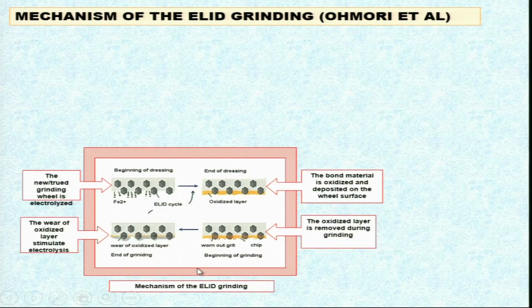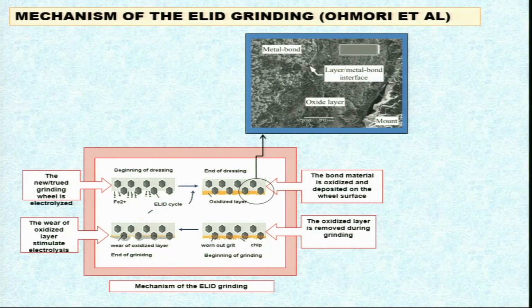You can see over here, more or less the same thing, the mechanism of the ELID grinding that we have seen. The new trued grinding wheel is electrolyzed. This is the new grinding wheel, and you can see the protrusion of the abrasive particles is quite large. But in the second phase, this is the oxidized layer being formed. So, the protrusion of the abrasive particle is continuously reducing, and if you go here, the oxidized layer is removed during grinding, because it becomes weak and larger forces are acting on the abrasive particle. So, they separate out or fracture and remove the oxide layer, and you have the worn out grit also, and chips are also there. This is the beginning of the grinding and wear of the oxidized layer, the end of grind, and this is the wear of the oxidized layer. So, the wear of the oxidized layer stimulates electrolysis.